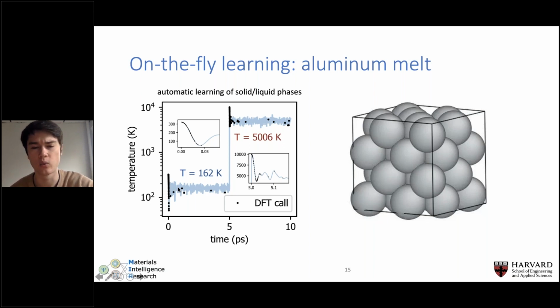And again, we're starting with nothing in the training set. So initially the GP knows nothing about the potential energy surface. Every black dot that you see here is a call made to DFT during this on-the-fly molecular dynamics simulation. At the very beginning, we need a bunch of DFT calls. You can see the cluster of black dots here. Then as the simulation proceeds, we need fewer and fewer as the model gains confidence about the forces in FCC aluminum.